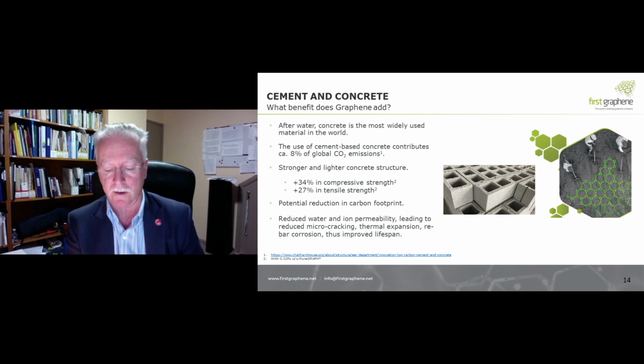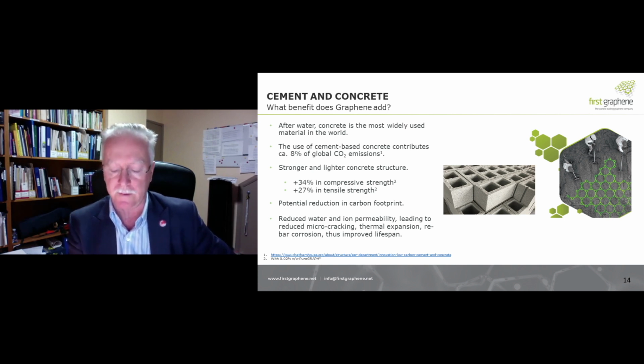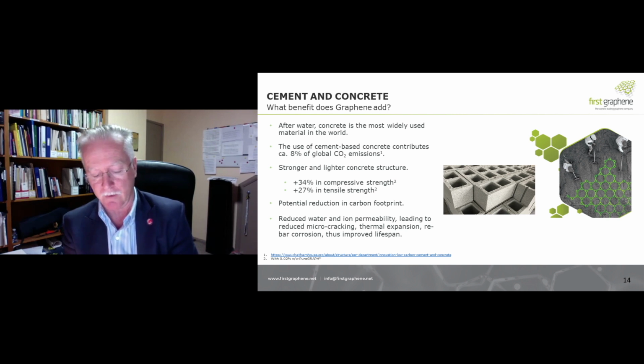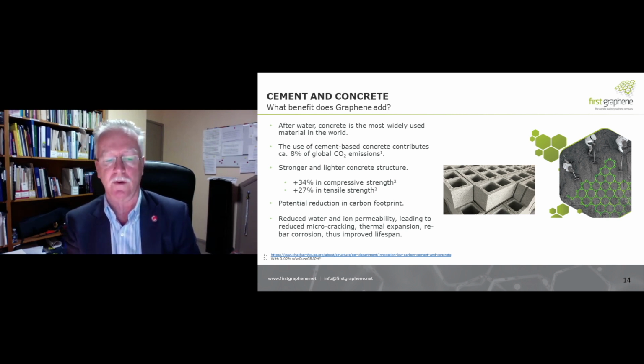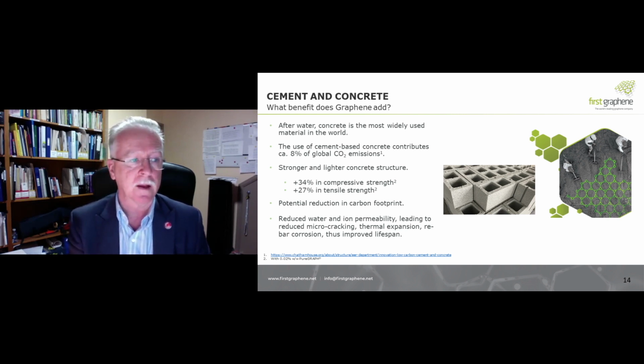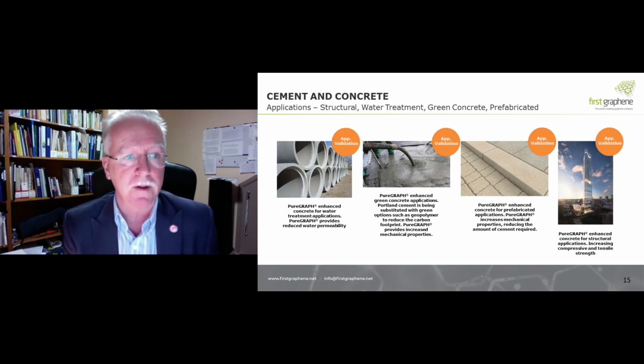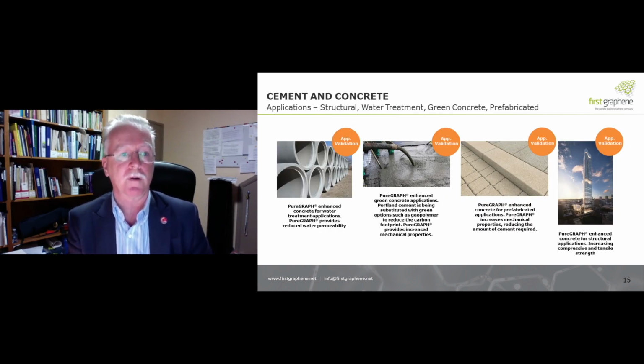It takes concrete a week to cure, and it does so inconsistently, which leads to micro cracks. The thermal conductivity of graphene assists in the flattening of the thermal gradient so that the temperature is more even as it cures. This leads to a significant reduction in micro cracks through which water can subsequently migrate to attack the rebar. Thus, graphene can significantly reduce concrete cancer. And here are some of the products that you could typically use graphene in: pipes, concrete slabs, tiles, construction.